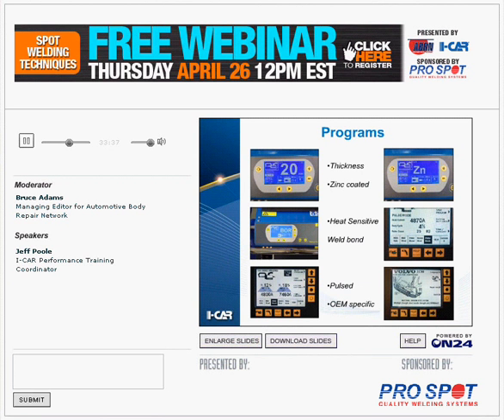Different coatings that might be on the metal affect its electrical properties, so here we have to take that into account. And with a zinc setting, again, a very popular coating on steels, that lowers the melting point and also lowers the electrical resistance. So we may have a pre-pulse of current that's applied to the zinc-coated steels. In other situations, we may have a call-out or a setting for heat-sensitive steels, such as our boron alloyed steels or dual-phase martensitics and things of that nature. This setting may have a more generic name, like a multi-phase as well.